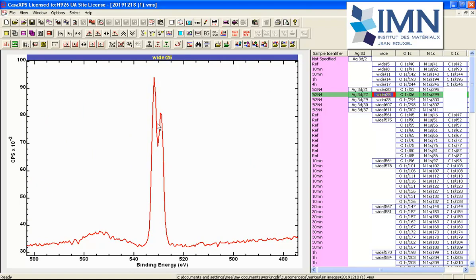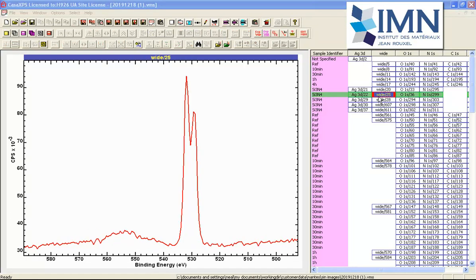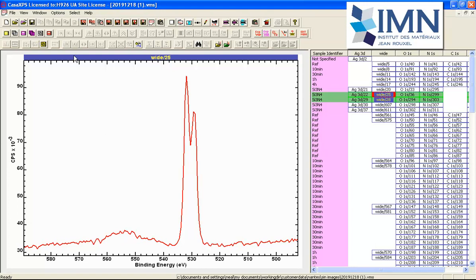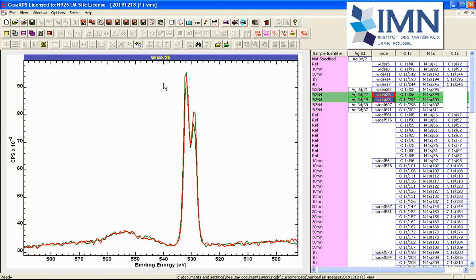Even with the charge compensation active, these data are not to be trusted in terms of chemical state. It's always a good idea to repeat a measurement. This next measurement is just a repeat of charge compensation. Even with just repeating the same measurement, we can see that there has been a small difference in the way these peaks are constructed.